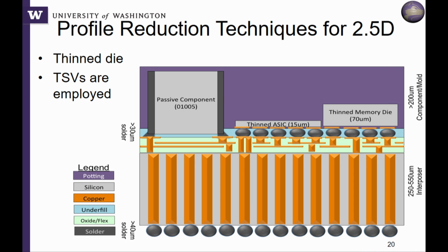If you look at the scale of the devices, the passive components are 01005, which is the smallest surface mount component available commercially still today. So you can see that the chips are not really the issue. The fact that we have passives embedded on this device increased the thickness substantially, and using a full thickness silicon carrier adds about 0.5 millimeter thickness.